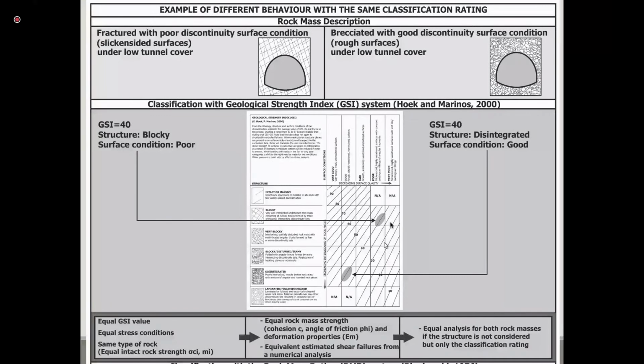So we have the same kind of material. Let's say this is a limestone and the same in situ stress regime. And when we use the GSI system and the observational chart, and it's the same if you use the quantified chart, it's absolutely the same. We will see that the first rock on your left will be projected here in the diagonal of 40 by blocky and poor combination. And on the right side, it will be projected again in the diagonal of the value of 40, though it is a very poor disintegrated rock mass with good rough surfaces.